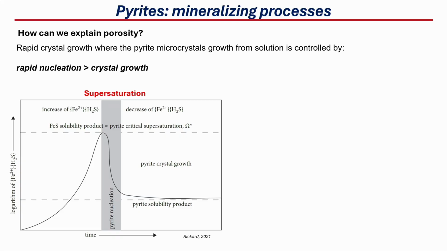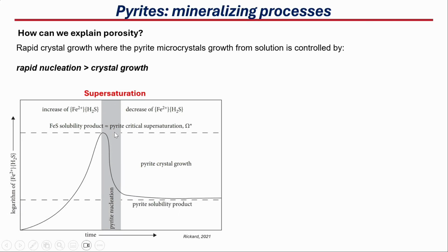And once it reaches a certain point, which is called the critical supersaturation, pyrite nucleation will occur in this region. After that is reached, actually all the fluid precipitates its content, and after that we have regular pyrite crystal growth. So we think this is one of the leading processes, and we can explain this with some evidence in